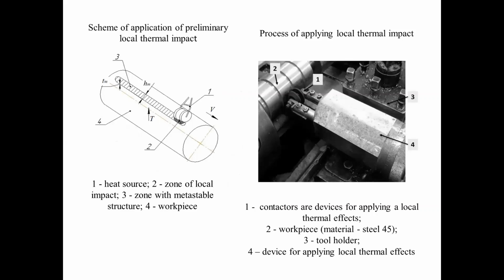To form a structure different from the main metal workpiece in the local zone, a device is used that implements the process of applying a local heat-affected line using the electrocontact method with a power of 27 up to 43.2 kilowatts. With the help of the device, a local heat-affected line is applied, along which a phase transition along a straight line is carried out.